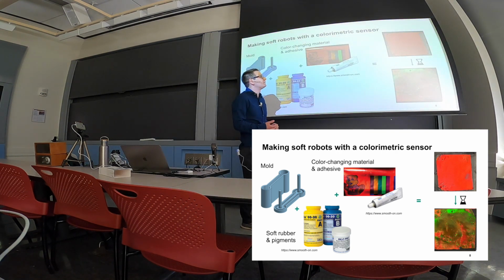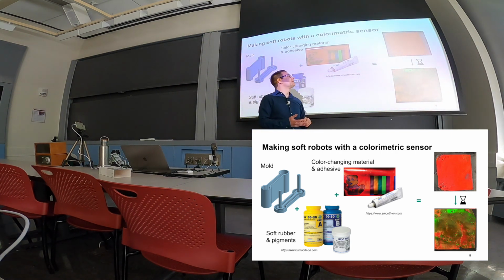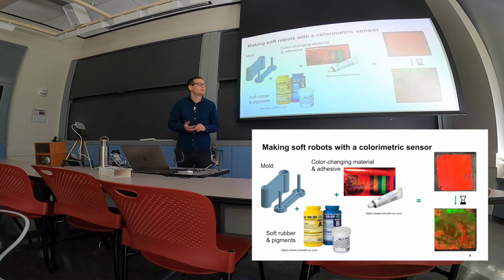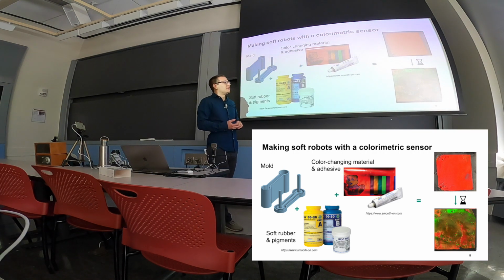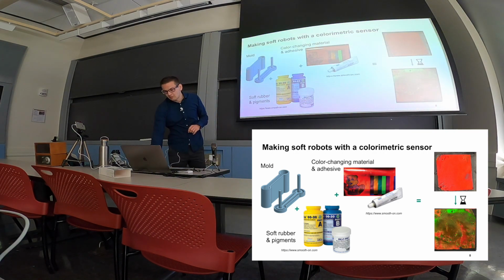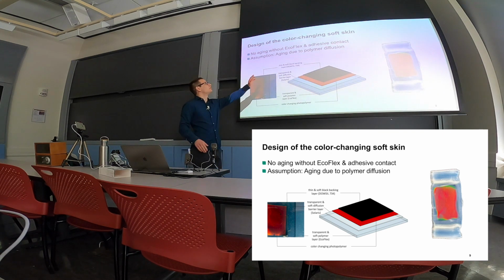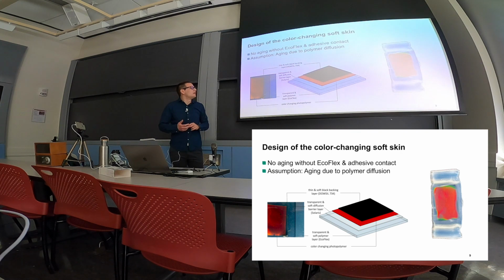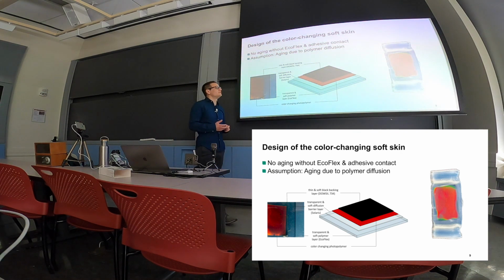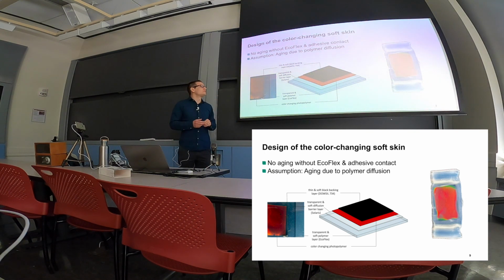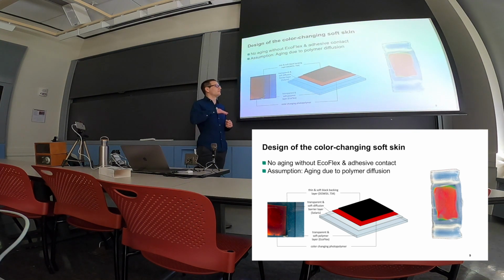Once I looked at those samples after a few days, I saw that it didn't look like this beautiful red sheet that we see on top anymore, but there was some inhomogeneous aging taking place, and a shift to green. And we knew that this shift to green did not occur when the color changing material itself was freestanding, so not in contact with the Ecoflex layer, and therefore we assumed that there might be a diffusion process, either of the polymers from the Ecoflex into the color changing material, or the other way around, which then probably leads to a deswelling and therefore a color change or a change in refractive index.